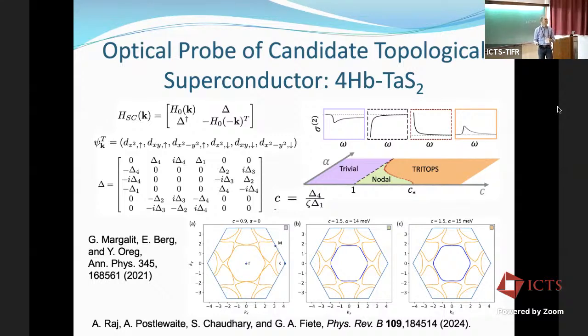And the question is, can you see anything in optical conductivity? And you do, in second order. So this is the main result, which is color-coded here. If you're in this orange phase approaching this boundary, you'll see some kind of divergence like this. Here, you'll see a divergence like this. Near this boundary, a divergence like that. And if you're on the trivial side, near that boundary, you'll see something which looks like this. So the shapes of these second-order optical conductivities with frequency are indicative of which phase you're in.